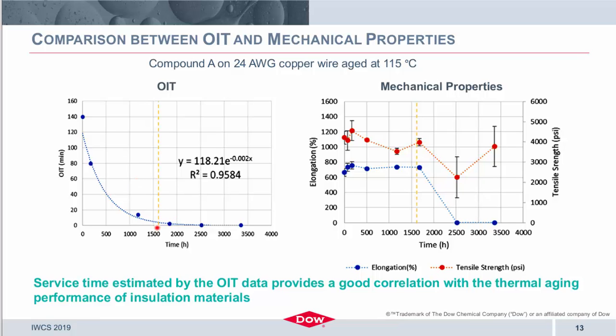Because in this case, 1,500 to 1,700 hours in aging for OIT would look very poor, but in reality, the mechanical properties are still very good. Now, they do fall off shortly thereafter, and what becomes difficult, especially when we start trying to talk about predicting service times, is that it's very difficult to capture samples within a given deterioration on the mechanical property side. So it's very difficult to know exactly when you're going to hit the 50% reduction over time without taking many sample points throughout that time period. But as far as service time and the prediction by OIT, it does provide a good correlation with the thermal aging performance of the materials.